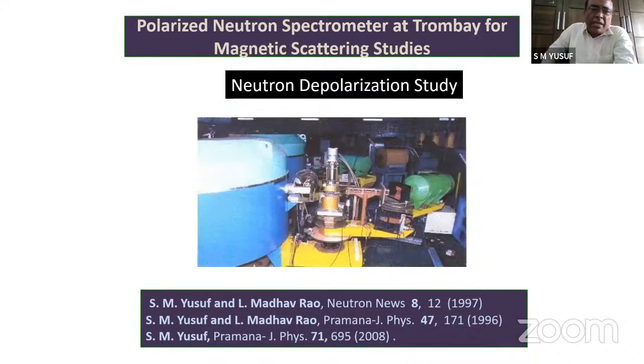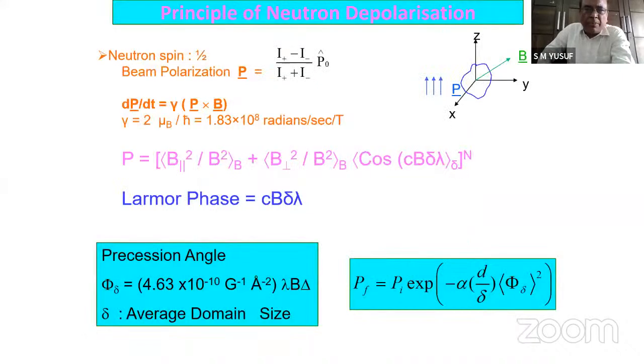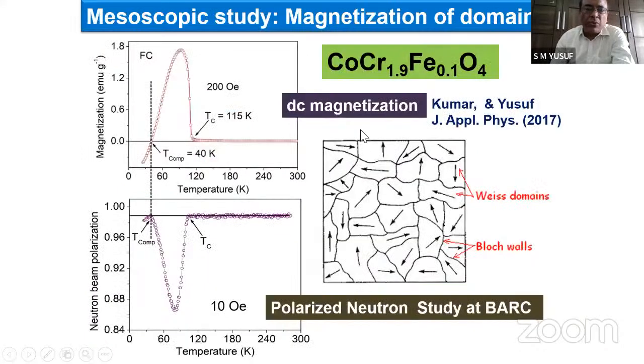We have used polarized neutrons in a so-called neutron depolarization study, where in the Dhruva reactor we pass polarized neutrons through this kind of magnetic sample. What happens when you have magnetic domains or magnetic clusters with net moment, and you pass the polarized neutrons with all spins up, if there's a net moment of a ferromagnetic domain or clusters, then there will be rotation of this neutron polarization. So in the outgoing channel, you will see the change of neutron polarization. By doing that, essentially, this is a technique where we directly see the mesoscopic object.